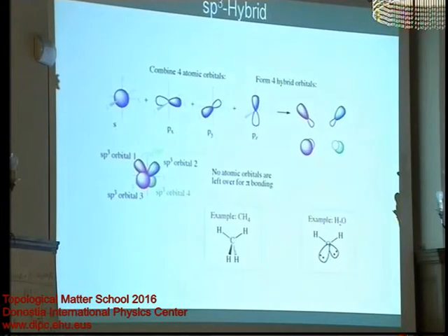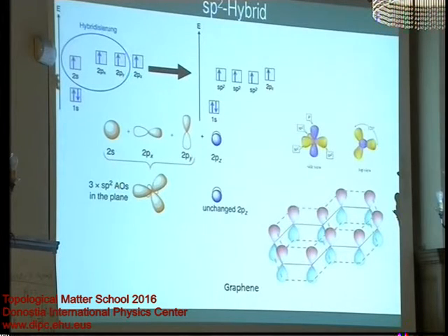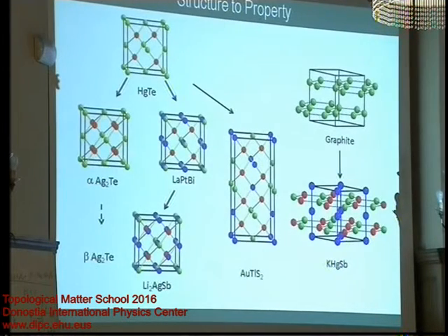So here, instead of the sp3 hybrid, we have an sp2 hybrid structure, and this is like graphene. Okay? In graphene, we have only one s electron and 2 p electrons hybridizing, and then one p orbital is left, which is perpendicular to the layer, because that is where we removed the additional atom. And so therefore we get this additional electronic structure here like we have it in graphene. Okay, and so you can find the electronic structure of graphene now also in these 8 or 18 valence electron compounds, and this was one idea which we had.